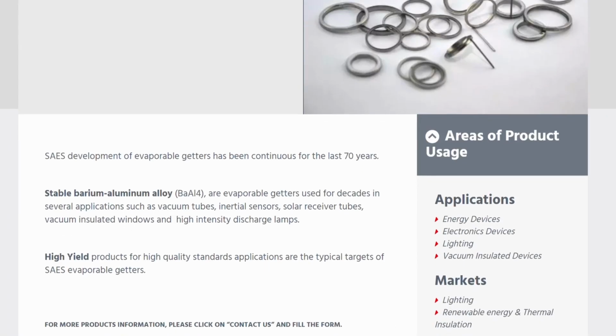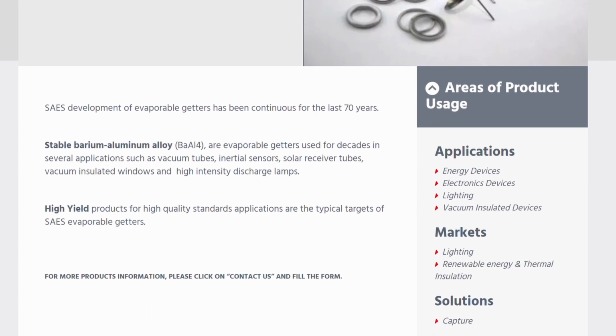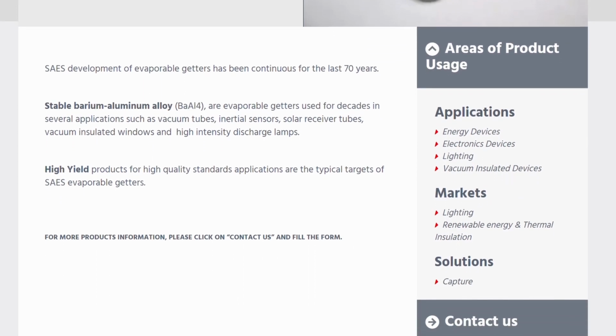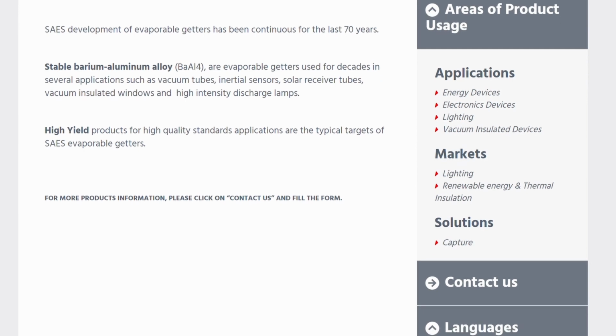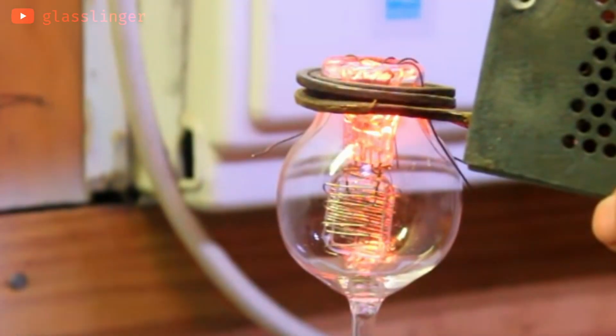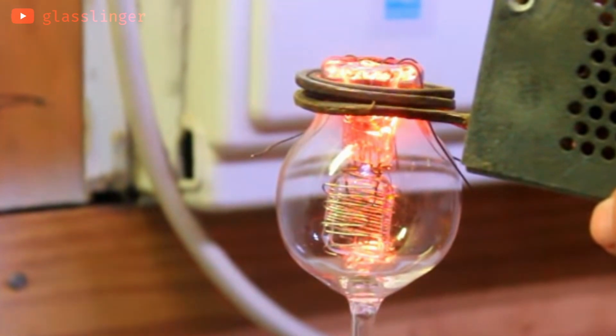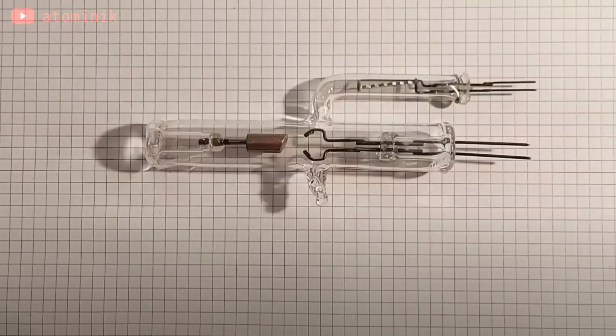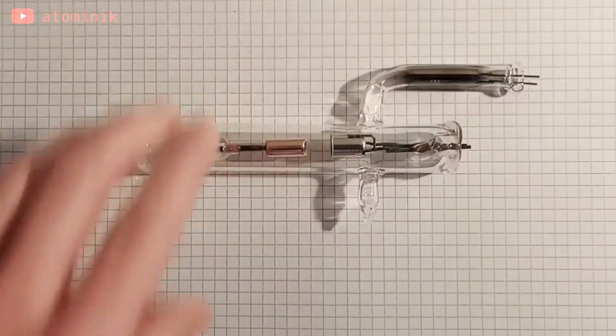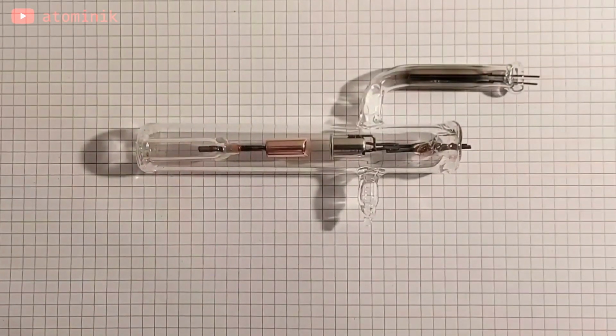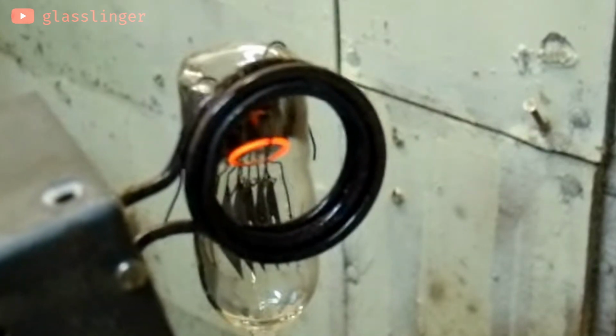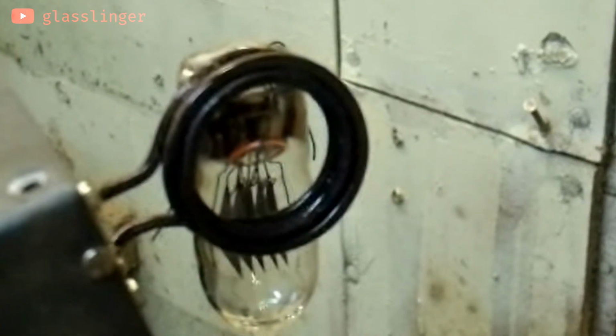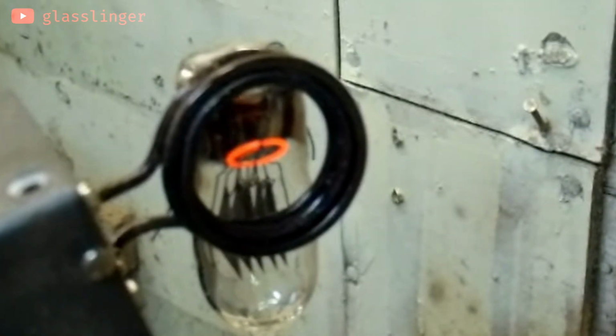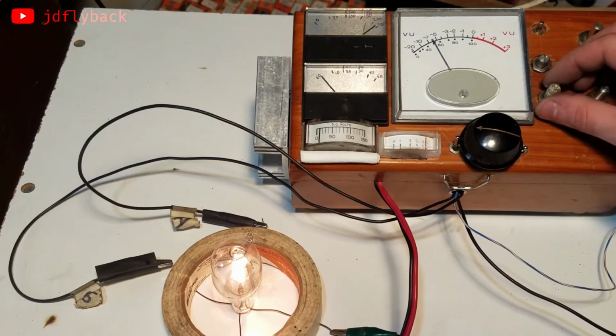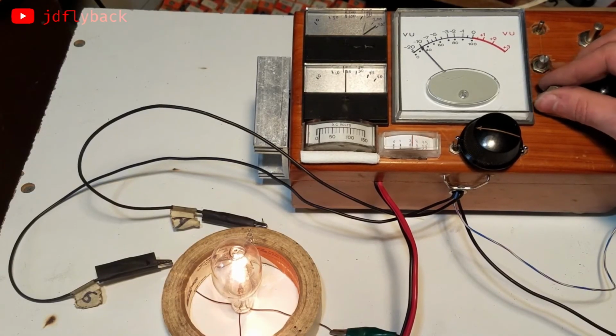To collect and sequester that oxygen, which has evolved over the life of the tube, we use a material called a getter. In the case of vacuum tubes, a getter is a metal alloy that gets vaporized and deposited on the inside of the glass envelope of the tube after it's sealed. This evaporation of the getter material, known as flashing the getter, is sometimes achieved by a dedicated filament, but more often than not it happens through the glass of the tube using induction heating. Popular getter materials include barium, strontium, aluminum, and titanium, and in the case of neon tubes, a little bit of mercury may be added as well. With the tube assembled and pumped down and the getter flashed, it's ready for operation.